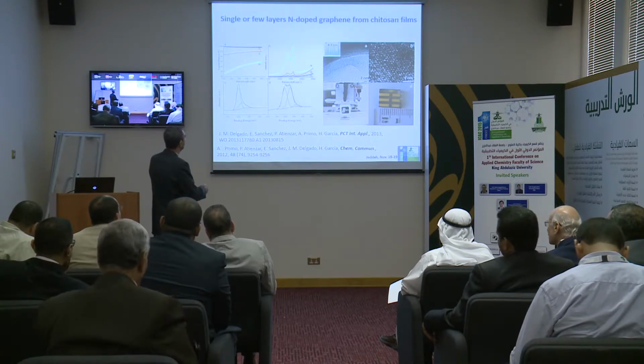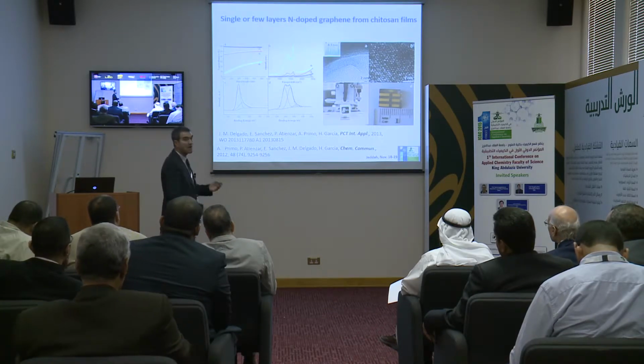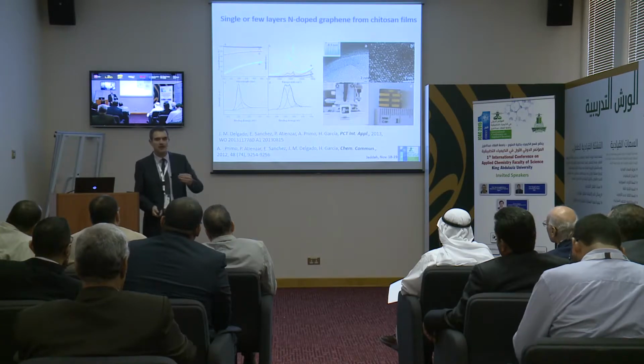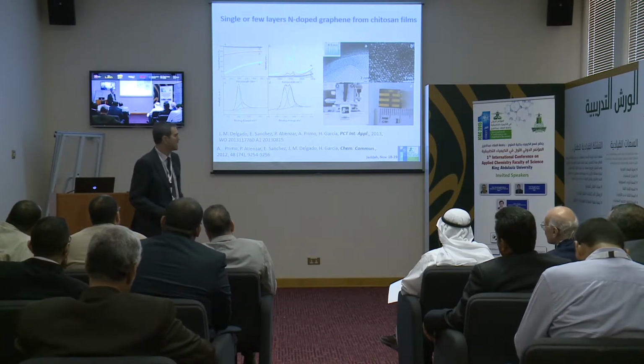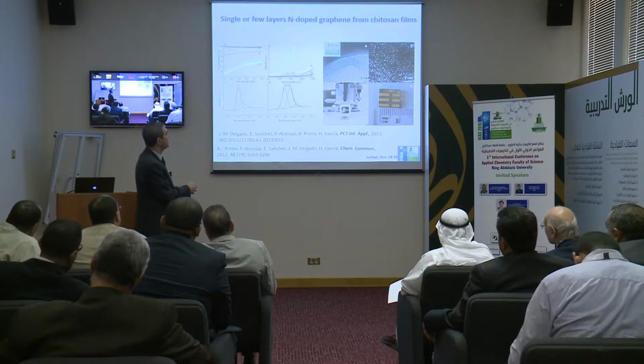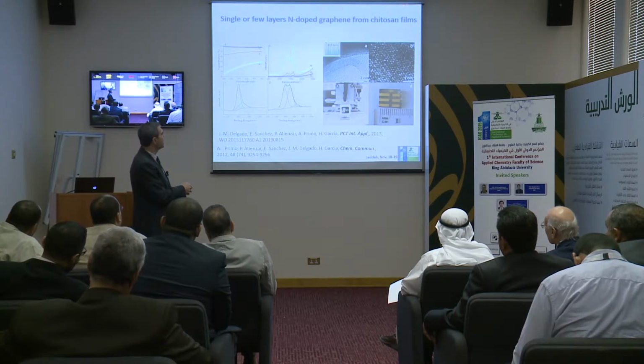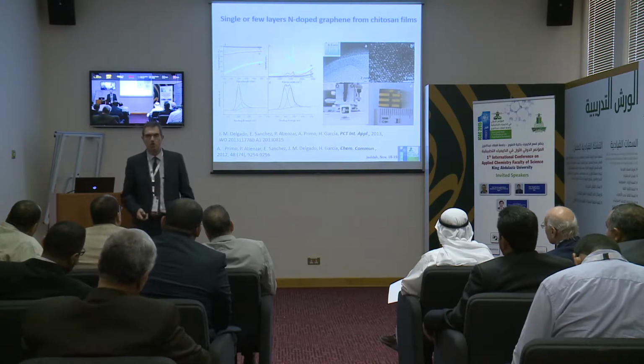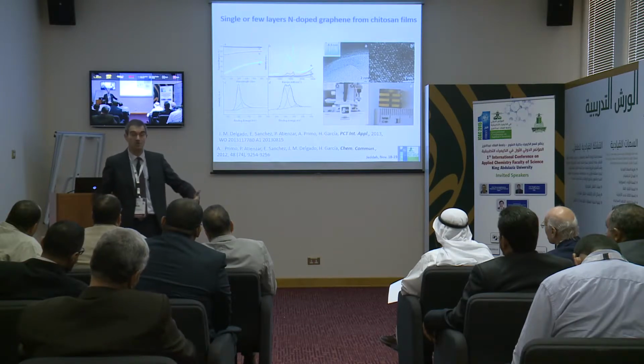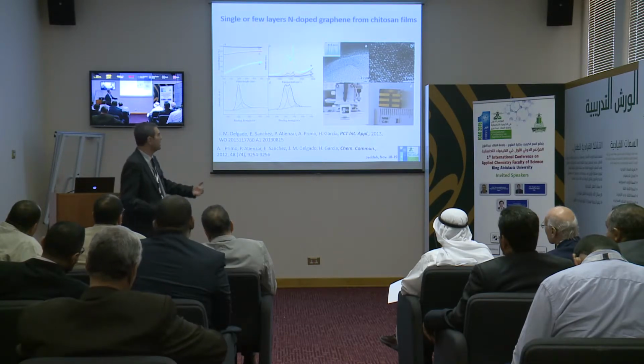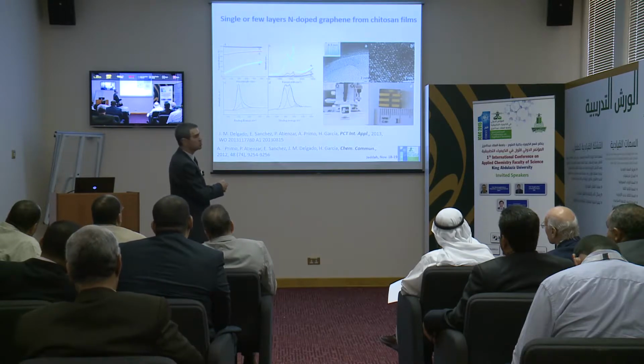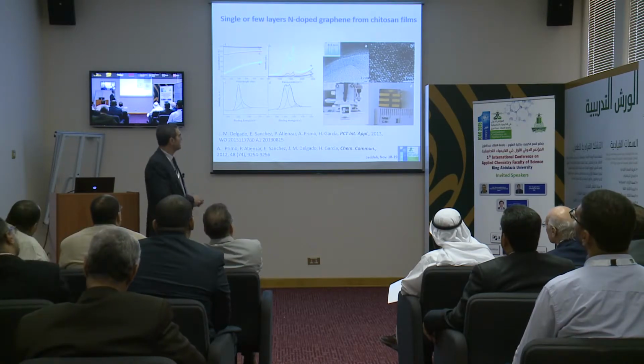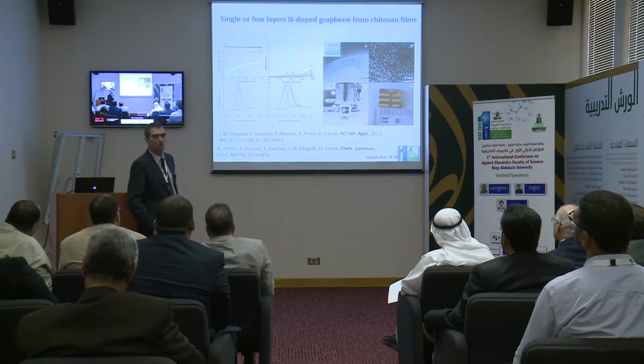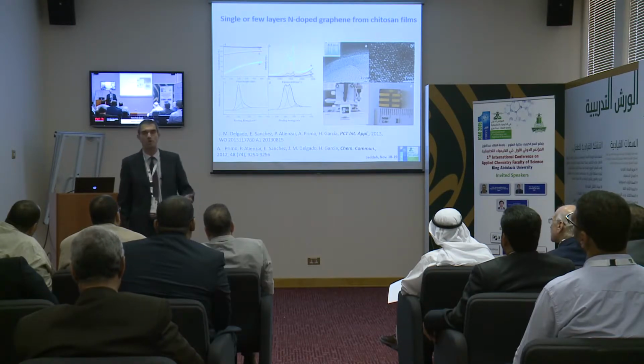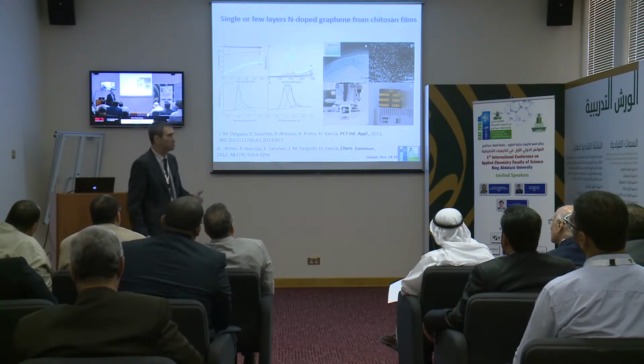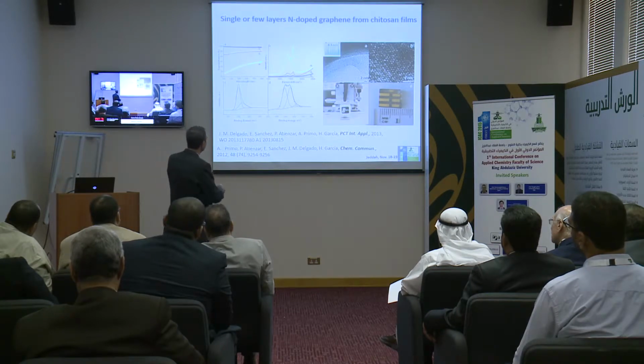Also in the case of chitosan, it is nitrogen doped, because we can prepare not only graphene made of carbon, but also graphene doped with heteroatoms. And in this case, what happens is that the precursor is a polysaccharide of glucosamine. So the natural compound already contains nitrogen, in glucosamine. When you pyrolyze, the 17% nitrogen content becomes reduced. But at the end, what you have is a graphene that contains about 7% nitrogen or lower, depending on the temperature of the pyrolysis.